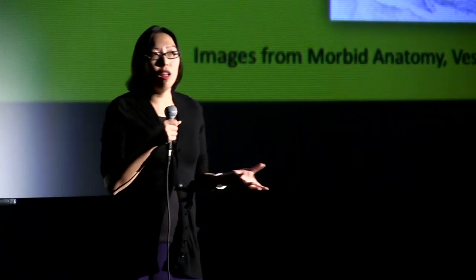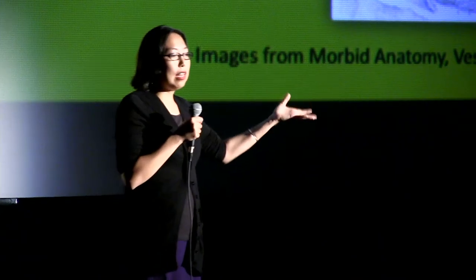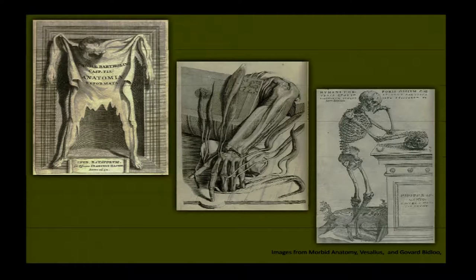Collagen molecules align themselves to create these fibrils. This is an electron micrograph, and they organize themselves so cleanly that they make these banding patterns. Depending on how tightly the collagen is cross-linked to its neighbor determines what kind of collagen it is. There are 30 different types of collagen molecules, and they can make up skin, tendon, and bone based on how tightly they're connected to each other. Bone, for example, has minerals embedded into the collagen matrix. So that's healthy collagen. Healthy collagen is why our skin is supple and why our tendons bend and why our bones are strong. But collagen can go really horribly wrong.